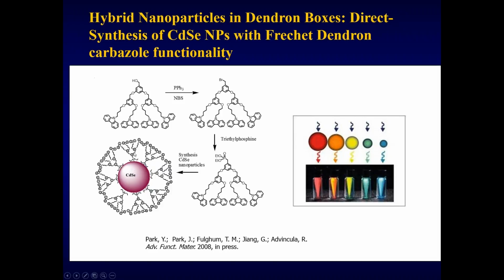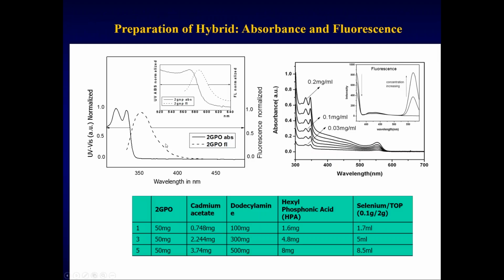Nevertheless, again, atomic force microscopy was vital, or one of the tools anyway, that we used to characterize the nanoparticles as we directly deposit them on the ITO surface. So this height histogram shows the corresponding diameters of the nanoparticles that were also consistent with some of our TEM imaging studies. So in principle, what we have here is essentially a cadmium selenide surrounded with carbazole dendrons, which can be electropolymerized intramolecularly, or as a film can be electropolymerized intermolecularly as well as intramolecularly. So by depositing this film on an ITO substrate, we can then electrochemically polymerize the carbazole units.